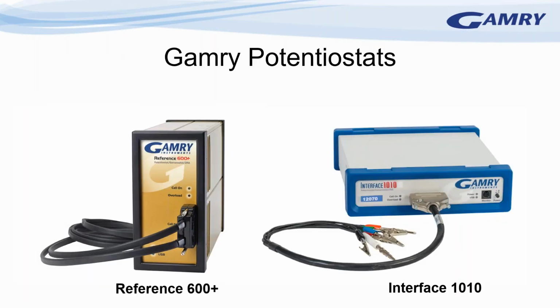So I'm just showing you a couple of pictures here of a couple of Gamry potentiostats. On the left is the Reference 600+, which is a high performance potentiostat that can measure very low currents, so for very small electrodes, if we've got small amounts of material. When I'm talking about low currents, I'm talking about going into the picoamp range. And on the right is the Interface 1010, which is a more general purpose research grade potentiostat, but it can also still measure pretty low currents, down into the nanoamp range.